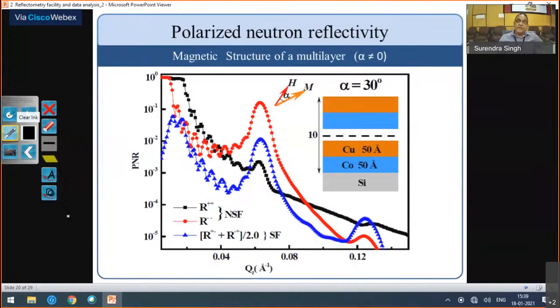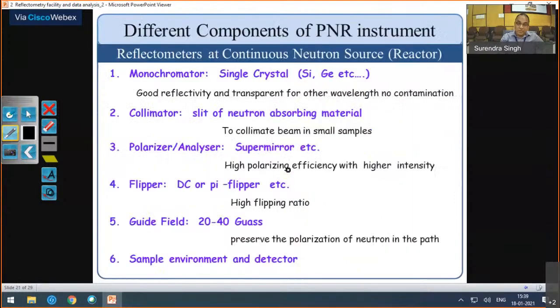This way we can determine that cobalt in a particular layer has this magnetic moment, and we get the detailed depth profile of the magnetic structure in our sample. So this is what I have already explained.